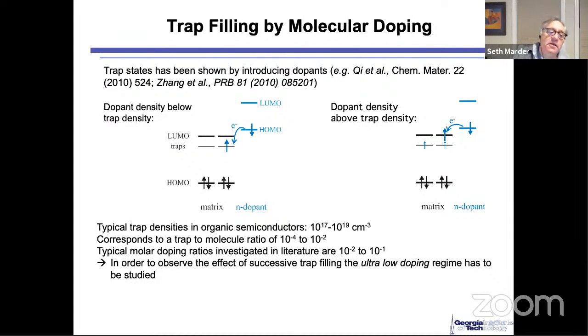The idea was the following: we would take a material that might have had some traps, not a terrible number of traps, but there are traps, and we would add a dopant where the HOMO was in fact above the transport level of the material. Initially we'd add enough of this to fill the trap states. But if we had a dopant density above the trap density, then we would start filling what we would call the transport states. And now we would see not only a modification of the mobility, but a relatively large change in